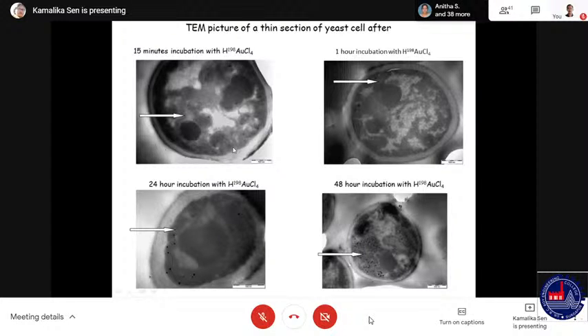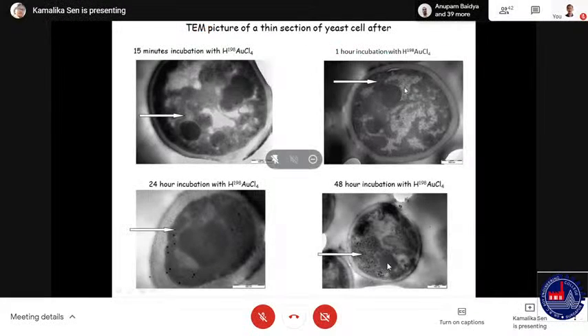formation have started. With time, say after 1 hour, small particles have entered the whole of the cell. You can see very small particles throughout. It has just clouded the surface of the cell. This is a thin section of the cell. After 24 hours, the particles have grown in size. These are larger. There are also smaller particles, but some particles have started growing in size.